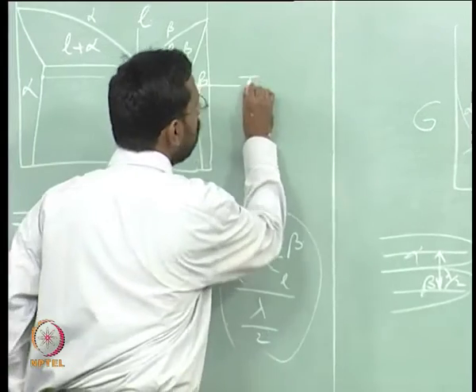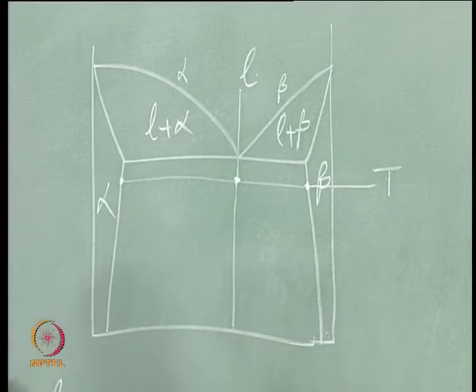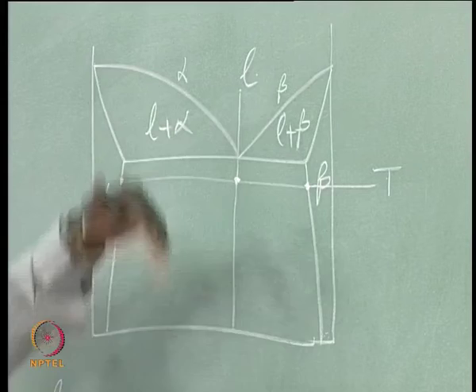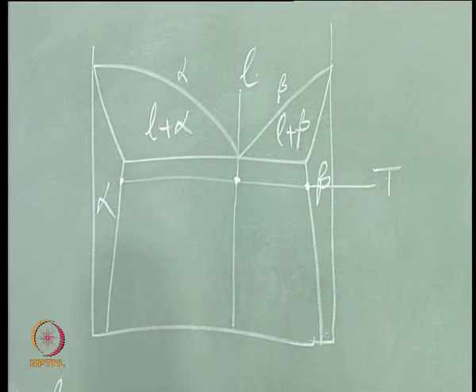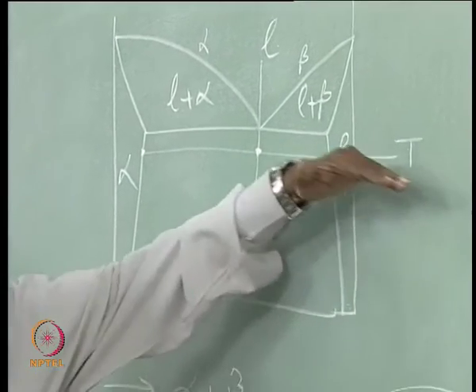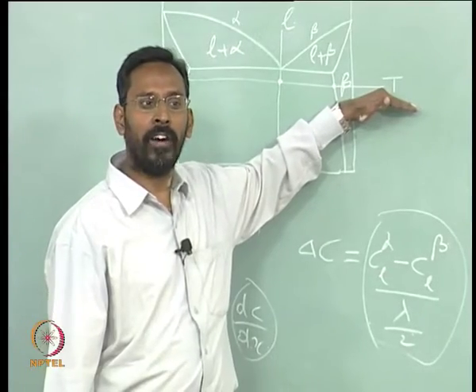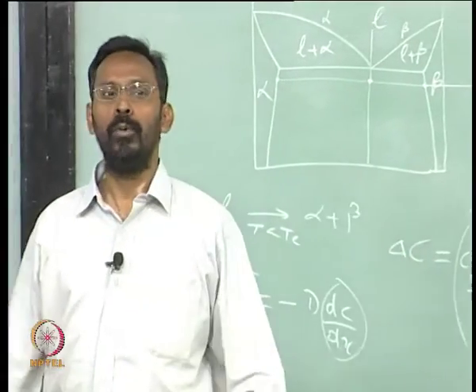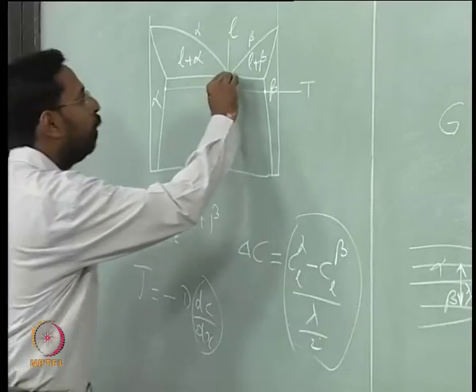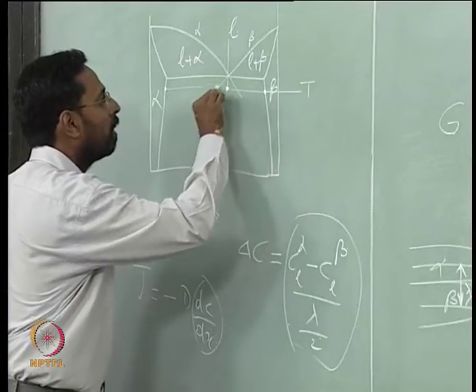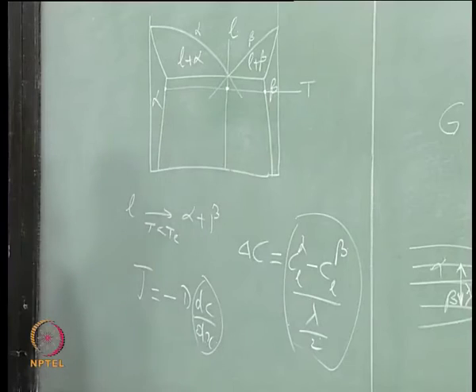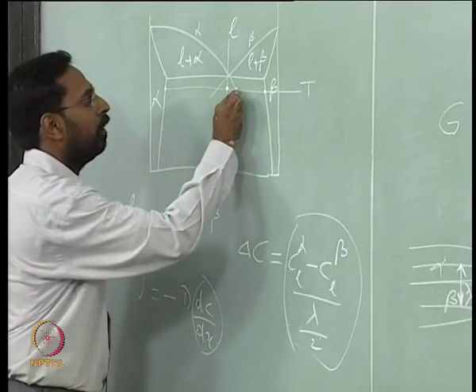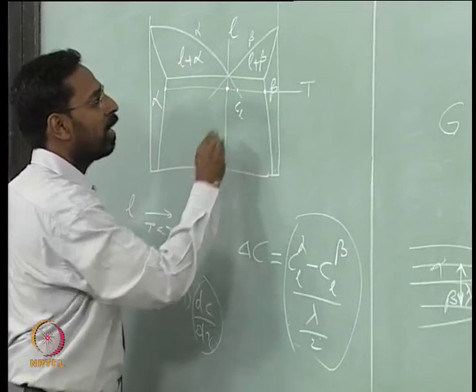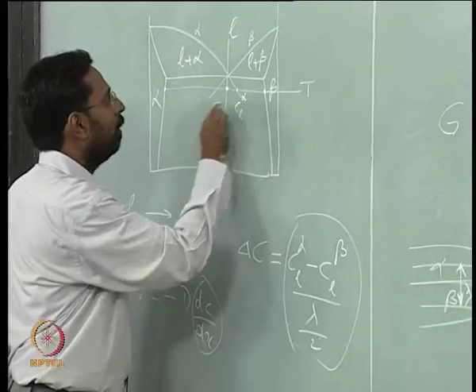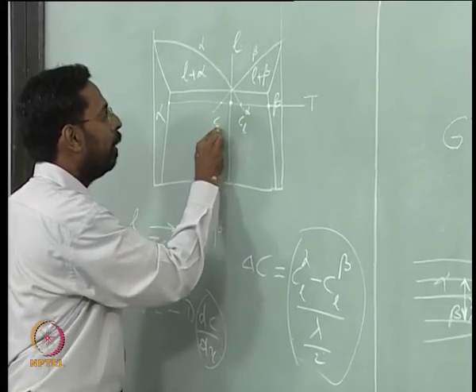So I want to know at this temperature T, what is that? If I want to know what is the composition of liquid in equilibrium with alpha and liquid in equilibrium with beta at that temperature, the only way I can find out is by extrapolating the two liquidus. So if I extrapolate the two liquidus, I get this, and this composition is nothing but Cl alpha. This is nothing but Cl beta.